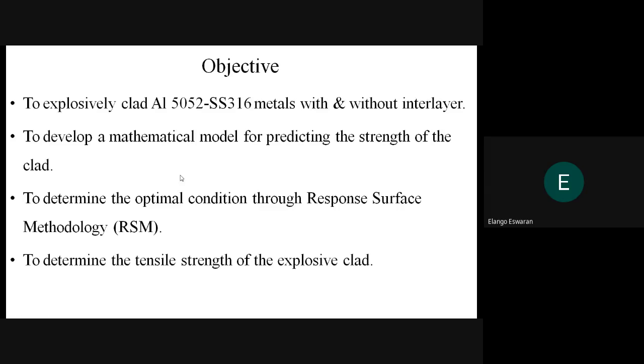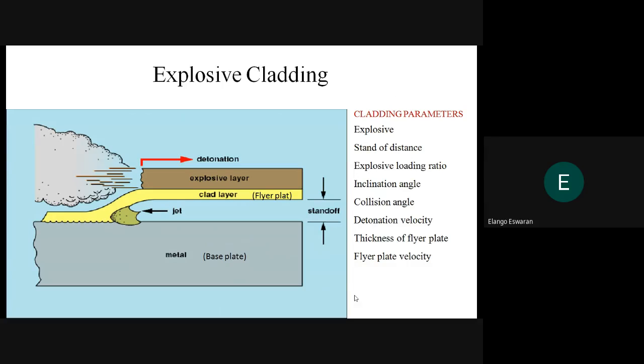The objective of the study is to explosively clad aluminum 5052 and SS316 metals with and without interlayer, to develop a mathematical model for predicting the strength of the clad, and to determine the optimal condition through response surface methodology, that is RSM, to determine the tensile strength of the explosive clad. In this process, a piece of metal is made to strike another under very heavy impact force, and the clad between them is achieved. A joining of large-sized components of difficult-to-weld metals are cladded by explosive cladding.